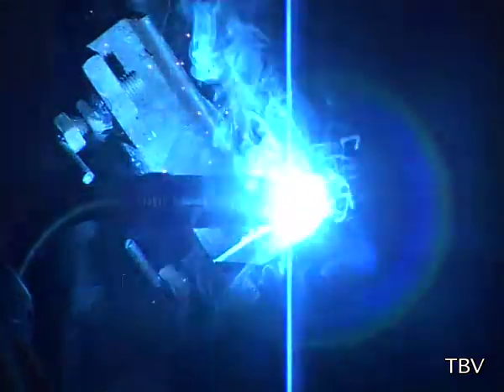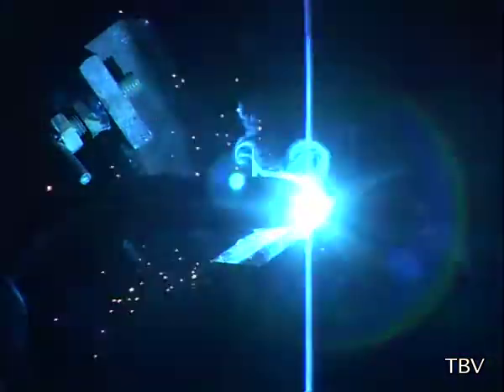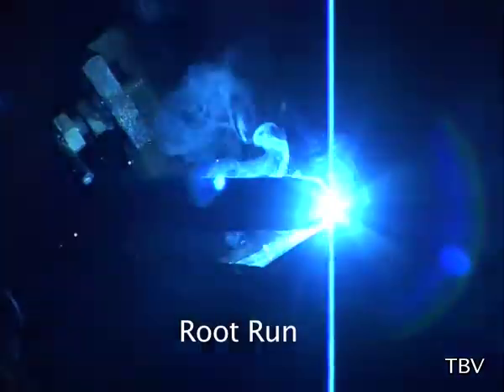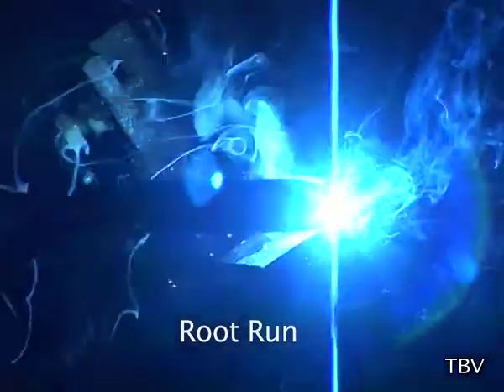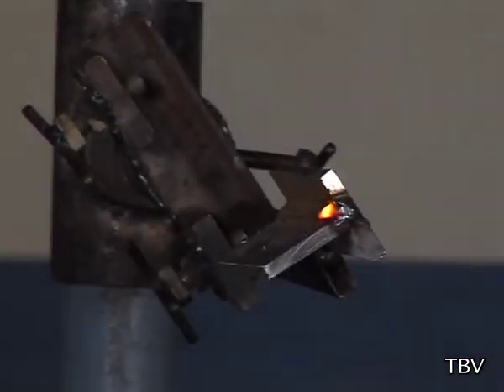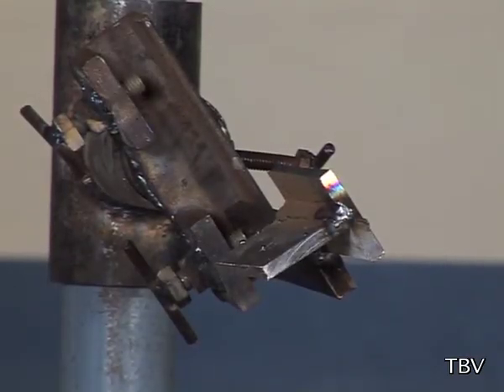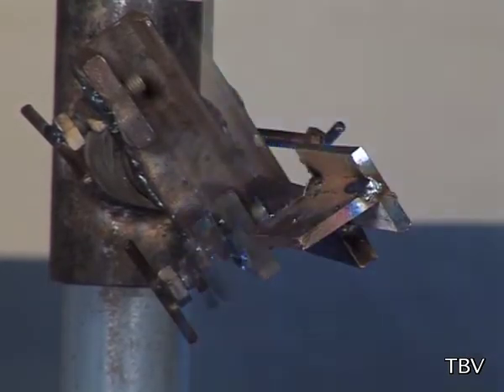As in the previous exercise, hold the torch at an angle of 10 to 15 degrees from the base plate and 45 degrees from the T-plate. Deposit the bead from one end of the T-joint to the other in the root run, or the first layer. Allow it to cool in atmospheric temperature for 5 to 10 minutes, then continue the second run as shown.